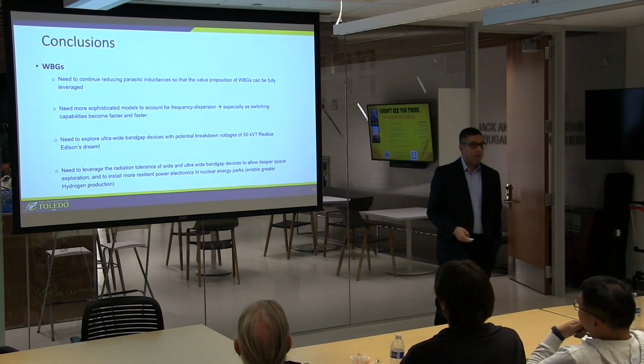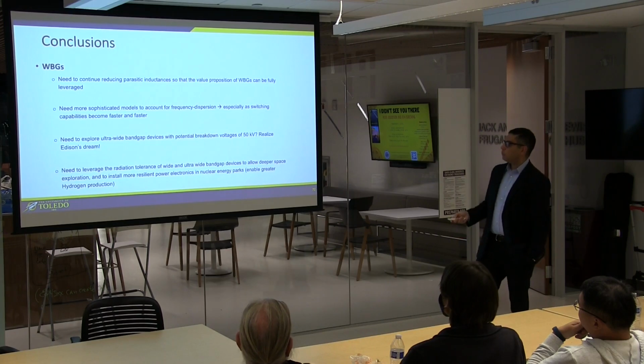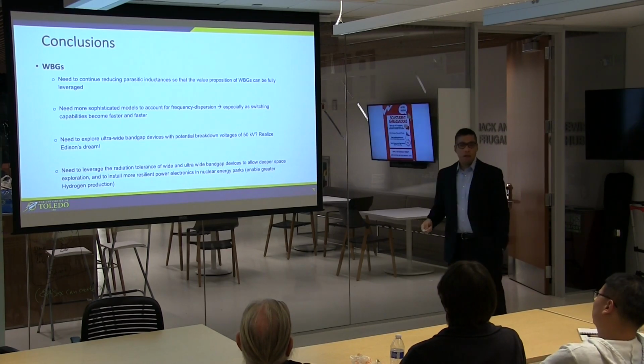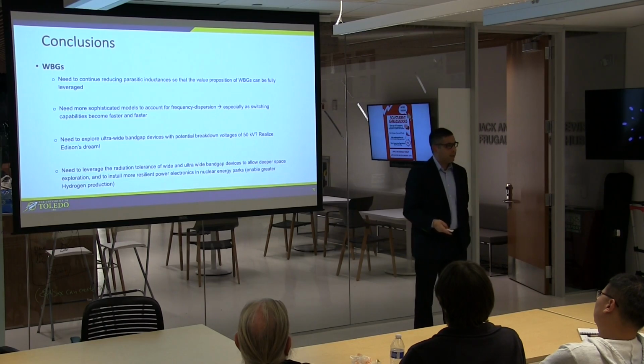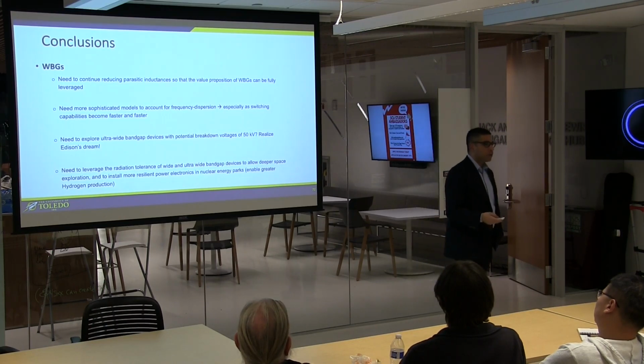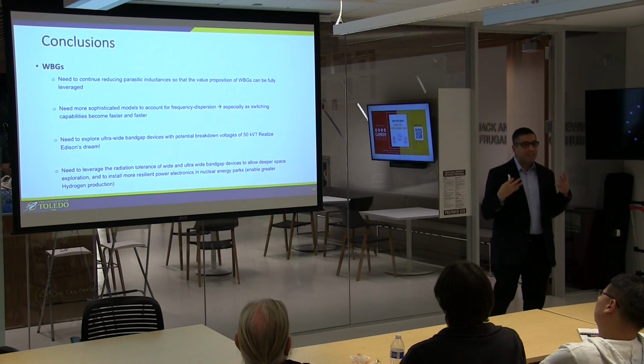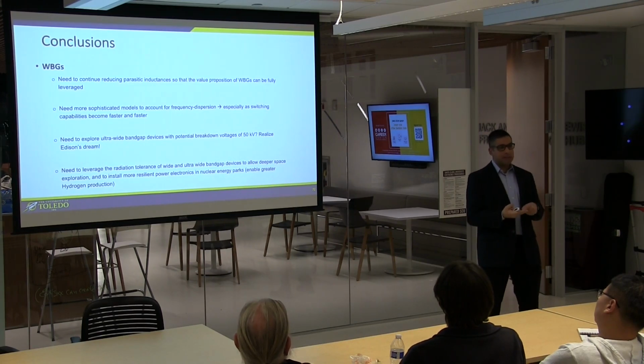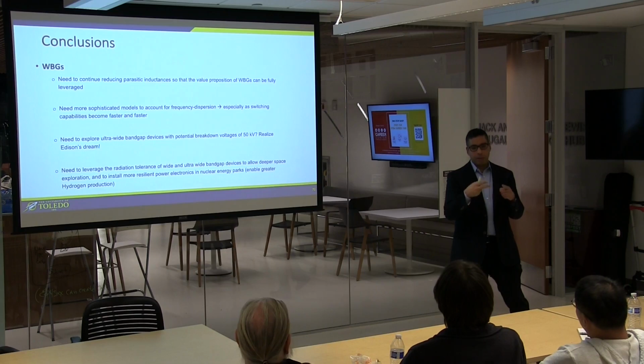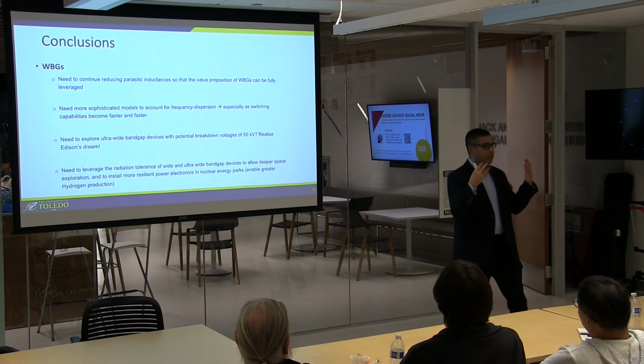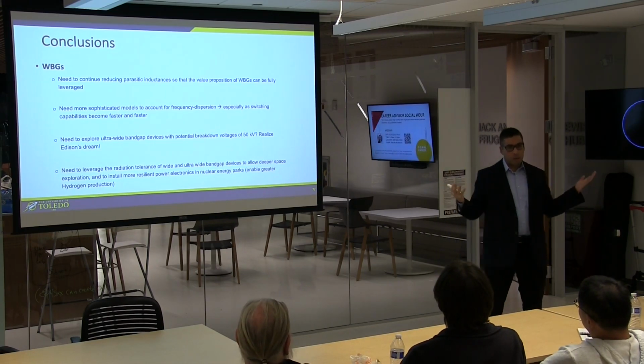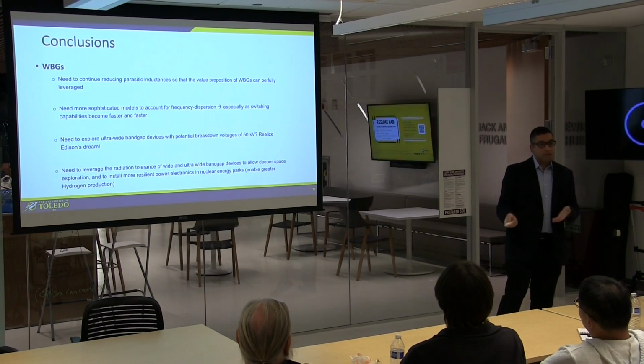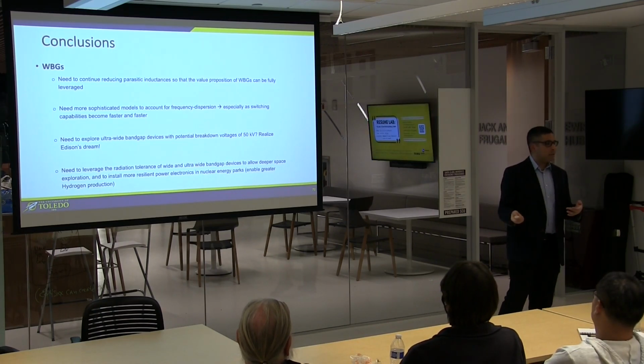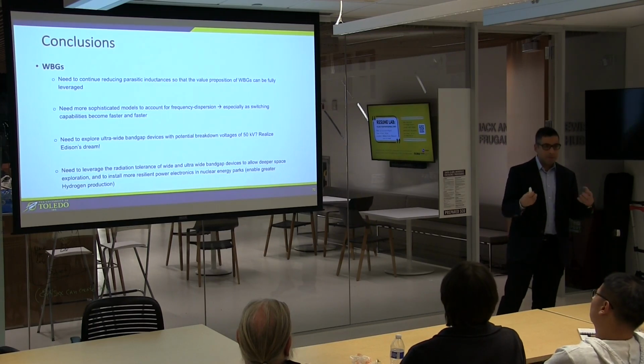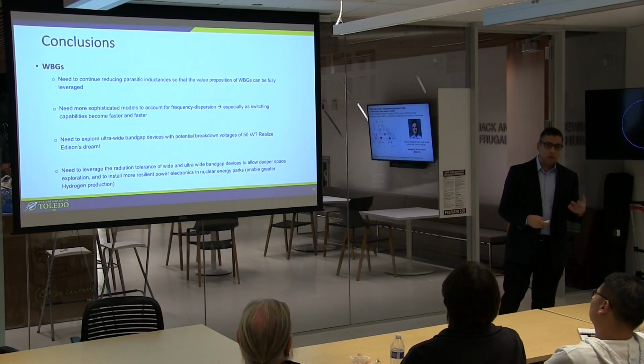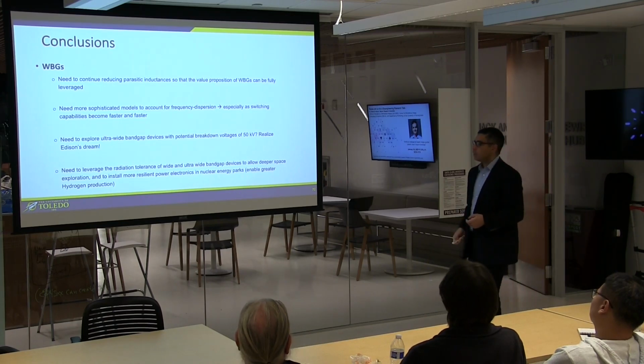As we move forward with wide bandgap semiconductors, we need to reduce the parasitic inductances so that the value proposition of wide bandgap semiconductors can be fully leveraged. Basically, a lot of times we find ourselves having to slow the device down, slow GaN down, slow silicon carbide down, because if we don't, then the parasitic inductances will disrupt their behavior, the thing blows up, and it's like, why? And then if you're slowing it down, it's basically no better than the silicon device. So we're not able to fully extract its value proposition. So we really need to work on fine-tuning parasitic inductance.